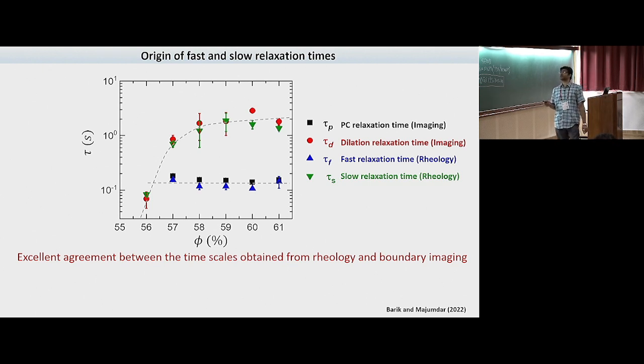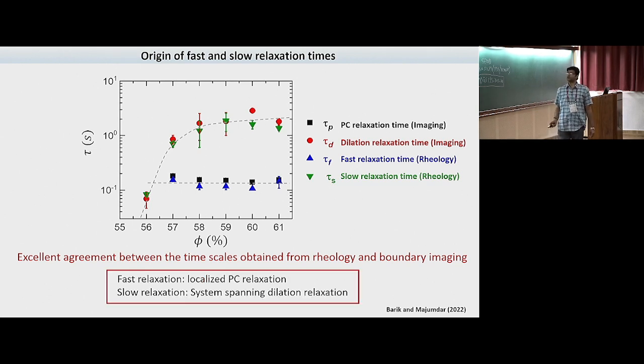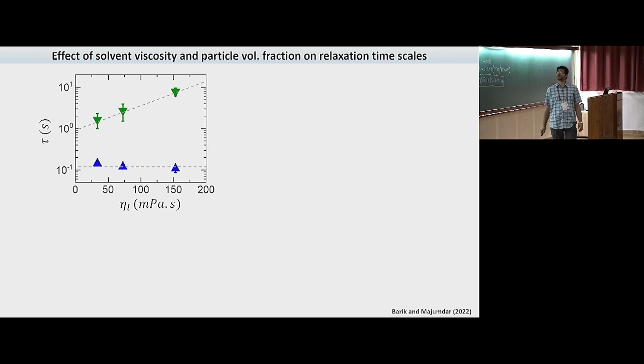Okay, so now we compared the time scales with what we got from stress measurement. We found that this plastic center relaxation time matches very well with the fast relaxation time scale, whereas this dilation relaxation time matches with the slow relaxation time scale for a wide range of volume fractions that show jamming. So we conclude that fast relaxation is due to localized plastic events, whereas slow relaxation is the dilation.